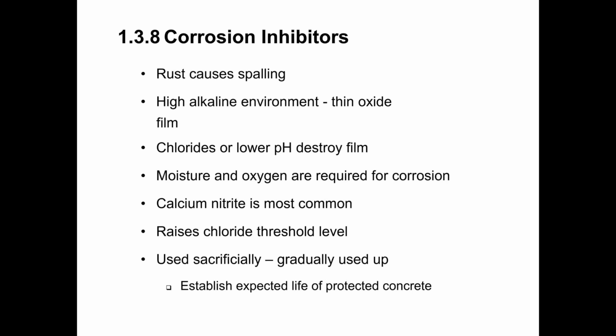All right, so as far as corrosion inhibitors are concerned, calcium nitrite is the most common that we see used. And what calcium nitrite does is it raises the chloride threshold level of the concrete. So it helps the concrete to protect the reinforcing from corrosion for a longer period of time. Now, keep in mind that corrosion inhibiting admixtures are used up over time. They are sacrificial. And so what that means is that you're going to get more protection the more corrosion inhibitor that you use. So depending on how that structure is going to be used in service and for how long that structure is anticipated to be needed, that will determine how much corrosion inhibitor is used.